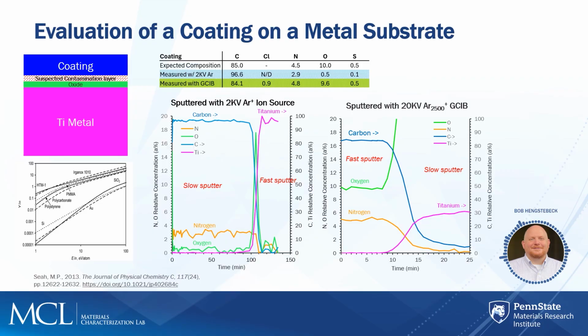All right, so let's take this back to the original example that I was showing you, where we had an interface oxide that we wanted to get an idea of what was happening with it. That specific oxide actually had a suspected contamination layer, and yet there was a coating on it. And we needed to remove that coating to be able to look at that interface. And this is actually an example of a material that was known to have a delamination issue.